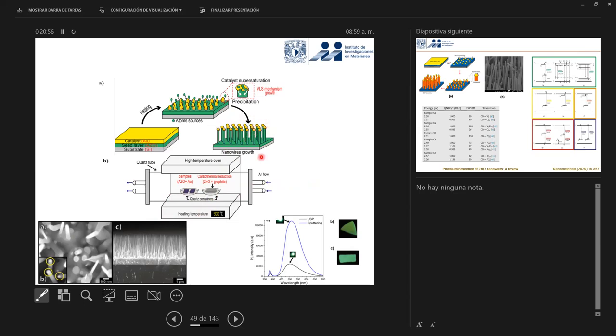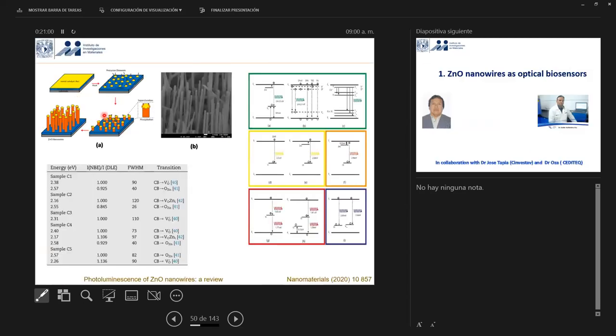So this was the technique, and then we studied the mechanism of emission from these nanowires, because it's an important topic for us if we want to develop different kinds of applications. We found that the different emissions arise because of zinc and oxygen vacancies, interstitial defects, and space charge vacancies.